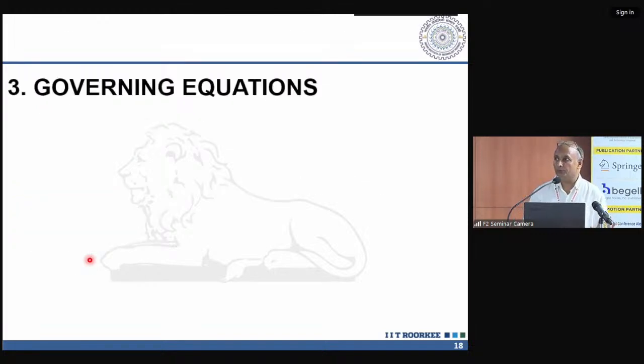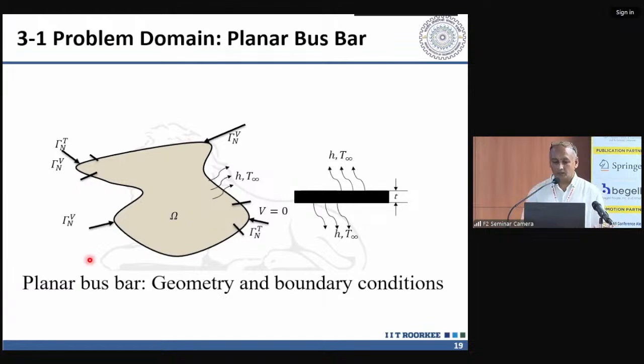Now, a brief overview of the governing equations which we took. Our focus to begin with was a simple planar bus bar. We had two sets of problems. The first one was a DC side. On the DC side, we will be using planar simple bus bars of specified thickness, because in industry, the copper sheets come in pre-defined thickness, 3 mm, 5 mm, and so on. Our focus was not on thickness optimization, because that will make the problem too complicated from a manufacturing perspective. So take standardized thickness sheets of copper.